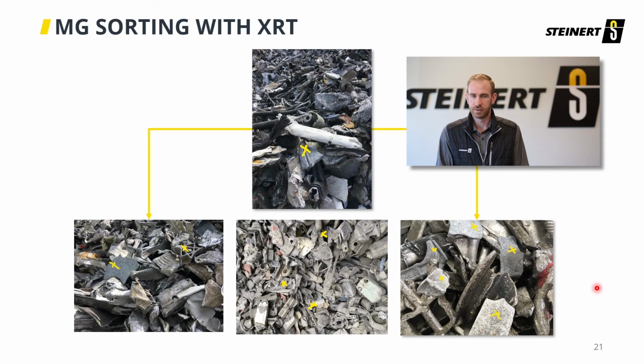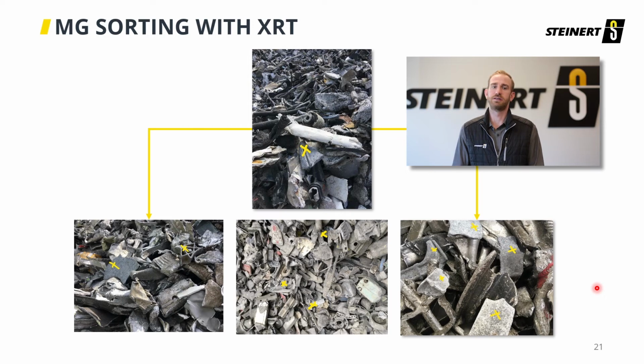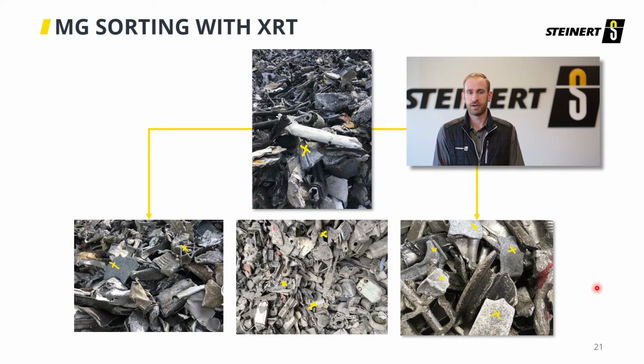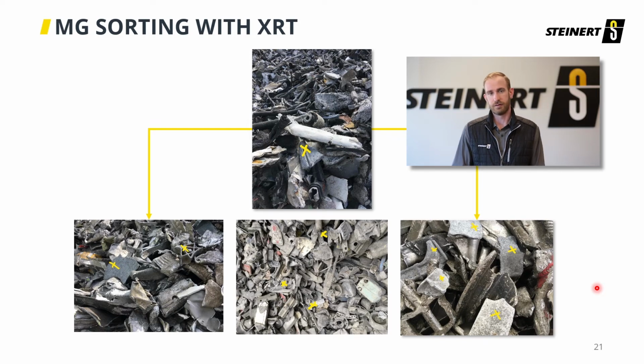So now let's talk about a special task with XRT, which is magnesium sorting. I mentioned it earlier, but free magnesium can be anywhere from say 0.5% to 3% or so in typical ASR scrap. And when you look at a pile, if you don't have a trained eye for it, you might not even recognize it. So what we see here is some pieces marked in yellow. So these are the ones with the yellow X's.